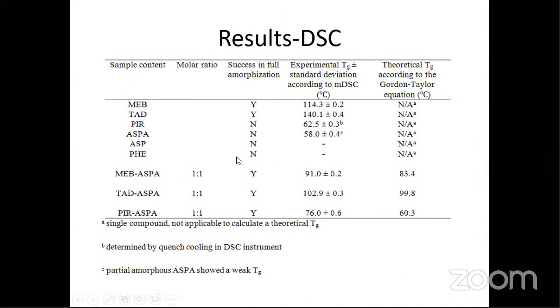And here we have the DSC results. DSC results, this is the pure compounds. We have the DSC here, have TG here, and also the coform, the mixtures, 1 to 1 mole ratio, right? And then we have the TG here. And this is a theoretical Tg according to Gordon-Taylor equation. And this is from theoretical, right? Theoretical TG. We can see it's almost the same.